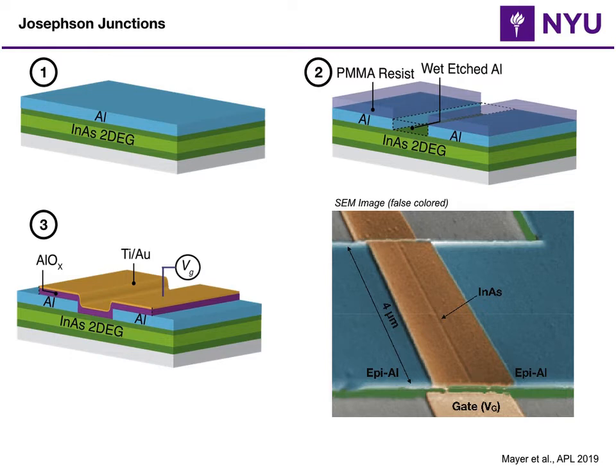So we start with aluminum on an indium arsenide 2DEG on the top left, and with an e-beam writer, we pattern the structure such that we remove a very tiny strip of aluminum, right? We can do that with a wet etch. This is Transene D etchant, which is very well known for aluminum. And then we put an aluminum oxide dielectric everywhere and a top gate, so we can tune the channel very much like a field effect transistor.